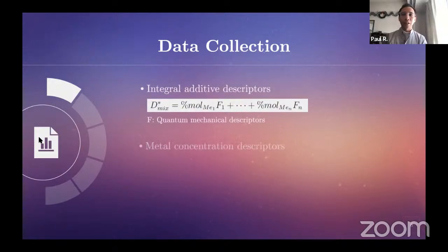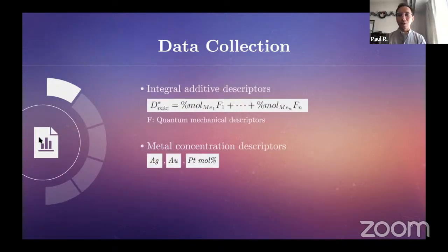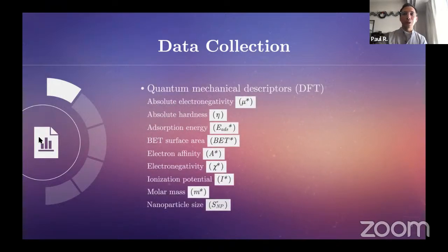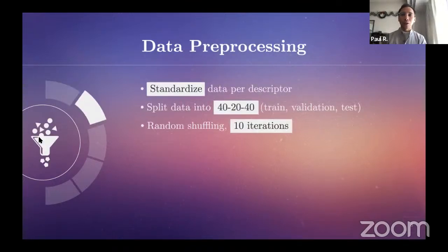Then, they applied integral additive descriptors to describe the weighted effect of different mixtures of nanoparticles to the overall property of the cluster. Using DFT, they calculated several quantum mechanical properties such as absolute electronegativity, absolute hardness, adsorption energy, and so on. Once we have these data samples, we proceed to the second step, which is pre-processing the data. Here, we standardize the data per descriptor. Then, we split the data into 3 sets for training, validation, and testing, following a 40-20-40 ratio. And finally, we randomly shuffle and split the dataset for 10 iterations.